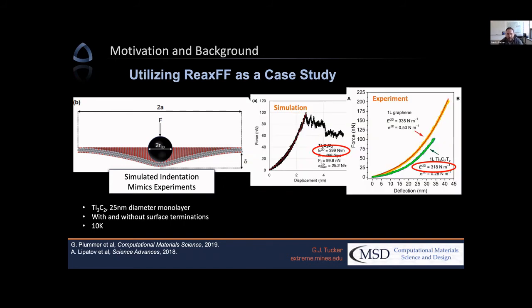So after we run these simulations, we get a force-displacement curve, and then we can fit that to a known model for these 2D materials, which gives us the 2D elastic constant. Shown here in the middle is the simulation data for Ti3C2, bare in this case, and we see that it approaches about 400 newtons per meter, whereas in an experiment from Lipatov and co-workers, we can see that the 2D in-plane modulus is about 318. And so the question obviously is why do we see such a significant disagreement in the resulting in-plane mechanical properties between simulation and experiment?